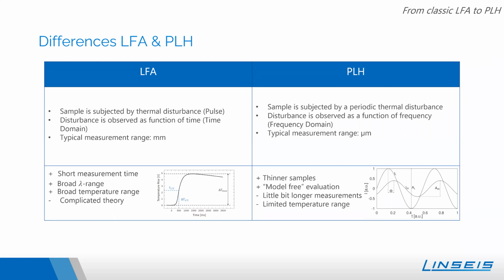On the other hand, the LFA evaluates the signal as a function of time. So you see, it's in the time domain. Also, the typical measurement range of an LFA is in the millimeter scale, while the typical measurement range for the sample thickness of the PLH is in the micrometer range.